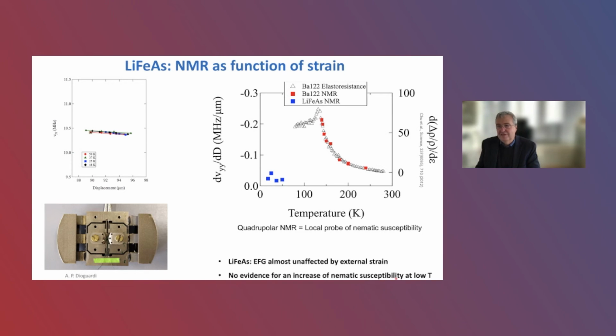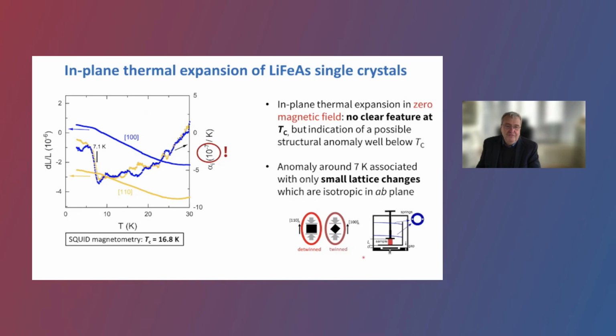That's just the message. And even worse, then we did a further very tricky experiment. We used dilatometry, looking for anomalies at the superconducting transition, which occurs here at 17 Kelvin. And this is basically noise, what you see here.